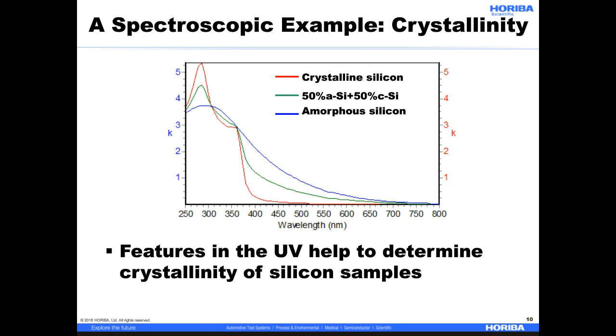I wanted to give two quick examples on how we use the UV to determine crystallinity. This is an example of three different curves. The red is crystalline silicon. The green is a 50-50 mix of amorphous silicon and crystalline silicon. And the blue is amorphous silicon.